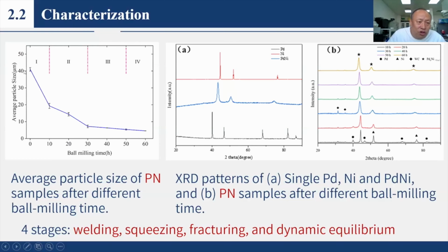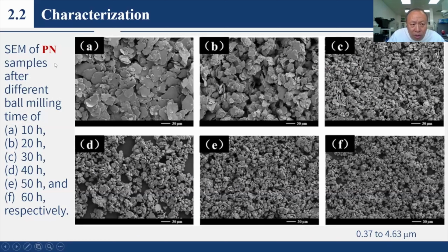We can find the average grain size goes from initially 40 micrometers to extremely around 4 micrometers. And figure B is the XRD patterns after different times. We can find that after 60 hours, there are only palladium-nickel alloys. This is the SEM of the PN samples after different times: A is 10 hours, B is 20 hours, C is 30 hours, D is 40 hours, E is 50 hours, and F is 60 hours. After 60 hours of ball milling, the grain size goes from 0.37 micrometer to 4.63 micrometer.